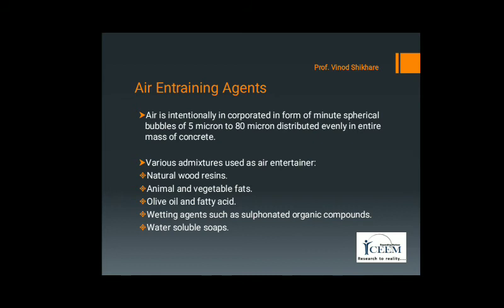At very low water cement ratio, water films on the cement will be insufficient to produce adequate foaming action. At intermediate water cement ratio, abundant air bubbles will be produced, but at a higher water cement ratio, though to start with a large amount of air entrainment is produced, a large proportion of the bubbles will be lost progressively with time.